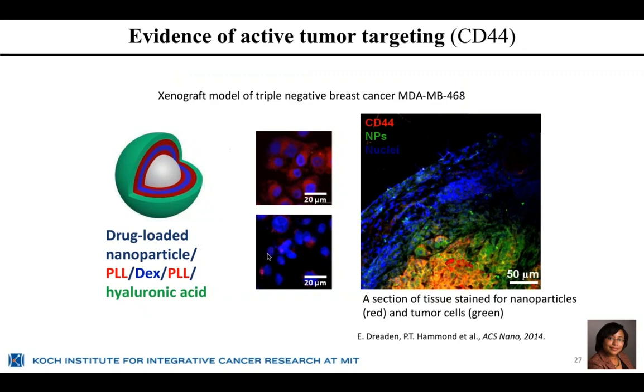In our case, it turns out that we have been using hyaluronic acid, a nice negatively charged polysaccharide that is present in our body as part of the matrix of our tissues, as the outer layer. Hyaluronic acid, or HA as we call it, is very highly hydrated and strongly negatively charged, and it has a large number of carboxylic acids on its surface. So we can essentially take advantage of the effect I described earlier of hypoxia to make these actively taken up by tumor cells. But it also turns out that hyaluronic acid binds a receptor called CD44, and CD44 is highly overexpressed on a number of the solid cancer tumor cells that we are targeting, including those in triple-negative breast cancer, non-small cell lung cancer, and ovarian cancer.